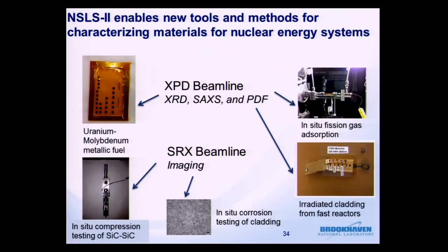We've also been doing some tomography and imaging of in situ compression tests of silicon carbide composites. This is some work we've been doing with General Atomics. And silicon carbide has the potential to operate at much higher temperatures than the other cladding materials that we've discussed. So for new reactors, it could potentially operate at much higher temperatures and provide greater efficiencies. So it's a very important material. However, it does fracture. So they're trying to improve the microstructure to increase the toughness and to really provide the barrier to fission product release.